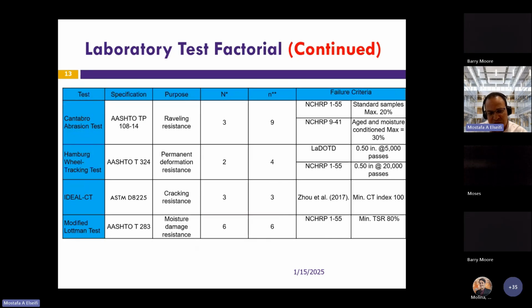In terms of performance, we conducted the Cantabro abrasion test, which is a very important test to look at the raveling resistance of OGFC. We conducted the rutting test based on the Hamburg wheel tracking test. We conducted the IDEAL-CT to look at the cracking resistance of the mix. And we conducted the modified Lottman test to look at the moisture resistance of the mix. So again, these 4 tests really give you a comprehensive assessment of the performance of the mix. And again, that's very important.